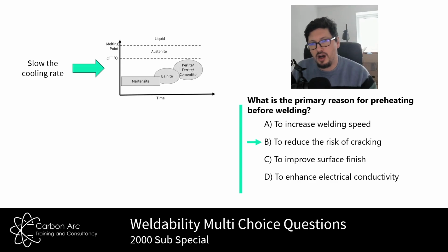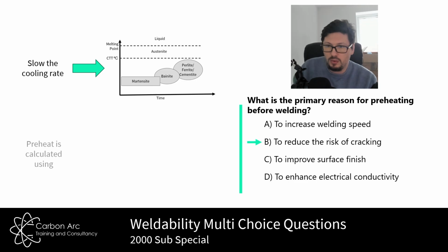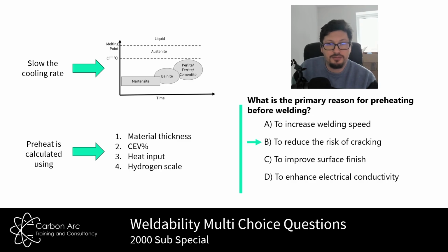Think of our TTT diagram and how that's affected by carbon. As carbon rates go up, the TTT martensitic band gets bigger, and we need to slow cooling more, right? Now, preheat is calculated using 4 different things. Okay, so material thickness, because the thicker the material, the faster it will cool.